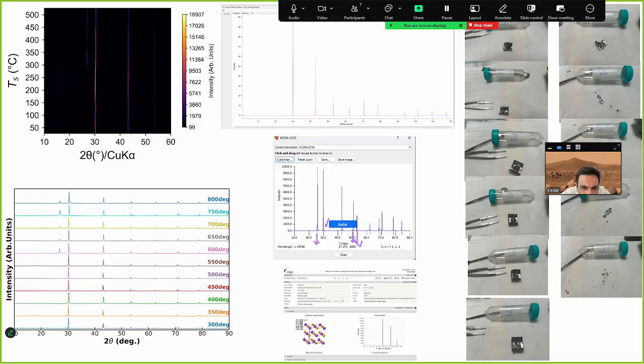These two peaks are the same for you, 30 and 42, right? Yes, same. That's good. That's the primary phase. You see, even the 50-something peak is there. So only two peaks are exact. I don't know if this is exactly double the 2 theta, so I don't know if it's the same crystal plane, which means there's some sort of ordering that is maybe not happening. That's my initial guess, but I'm not confident.